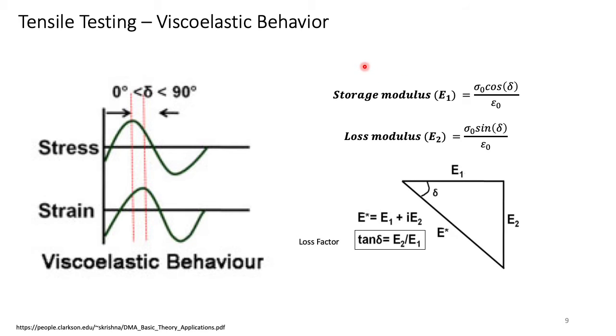So how can we measure the storage and loss modulus of the material using tensile testing? We first apply an alternating force, and then we find the stress and strain plots, and by comparing these plots we can find the phase angle that helps us understand the viscous or viscoelastic behavior of the material.